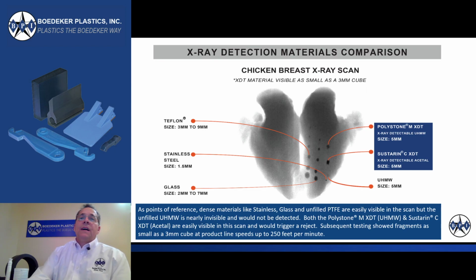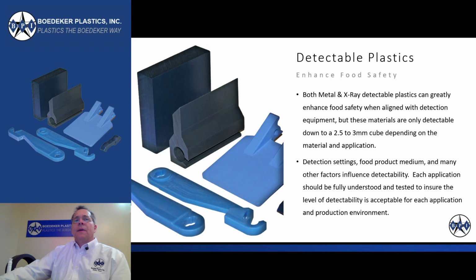So to give you some relative terms, so you can have an understanding of how the test went, this chicken breast moved down the production line at about 250 feet per minute, and you can see the level of detectability even at those speeds. So again, hopefully it gives you a little bit of an understanding of what you can actually expect to see from these detectability polymers.